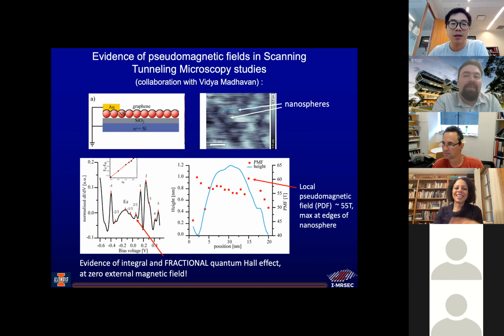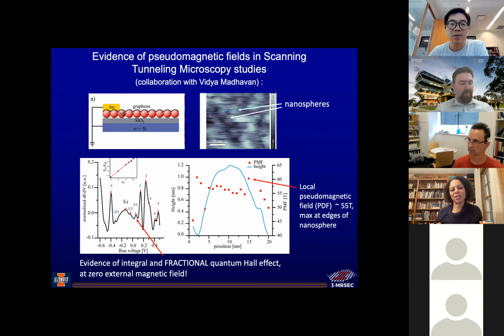So the problem is that they can make perfect lattices that are long length scale by putting ligands and other things between the nanoparticles. The problem there is, one, they're generally not single layer. When they do this, it's often sort of crystals of them, and we really want one single layer. The other is that the more chemistry you do to it, the dirtier our graphene gets. And so when they started putting ligands between their nanoparticles, we started getting just really broad Dirac points.